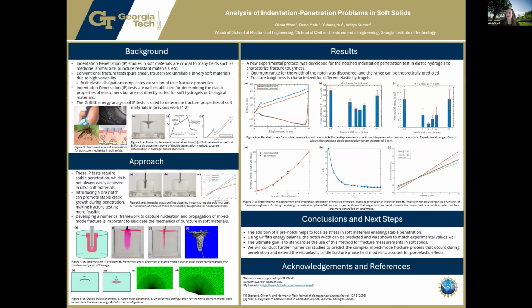Now I'll go ahead and highlight our key results. First, we developed a new experimental model for notched indentation penetration tests in soft solids. In Figure 6, you can see force displacement curves for these tests. And unlike traditional methods, the curves show stable and repeatable behavior, which is critical for reliable measurements.